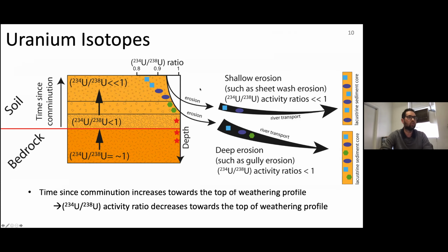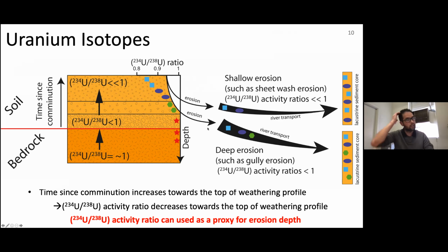But if we think about erosion, what then actually happens when we start to mobilize our material is, if we have shallow erosion, such as, for example, sheet wash erosion, we would particularly mobilize this topsoil layer. So we will find material that is deposited in our sediment core with very low activity ratios. On the other hand, if we have deep erosion, such as gully erosion, we have activity ratios in our sediment which are closer to 1. So we can also use the activity ratio as a proxy for erosion depth.